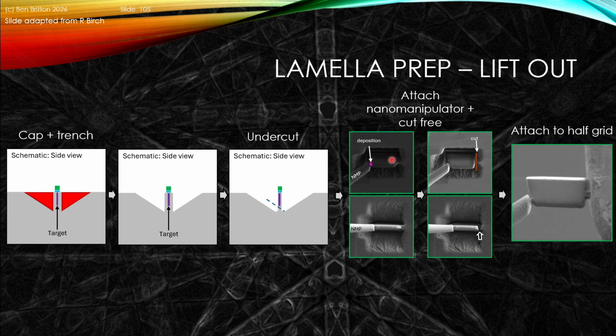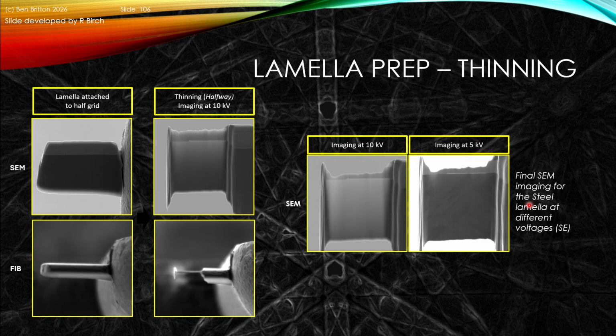So now this lamella is simply attached to the nanomanipulator. We can then pull the nanomanipulator upwards with regards to the surface to liberate it, move the sample out the way, and bring it and attach it to a half grid. We'll weld it onto the half grid, and then we'll cut it off the needle as presented here. Once we've mounted it on the grid, we can then perform thinning.